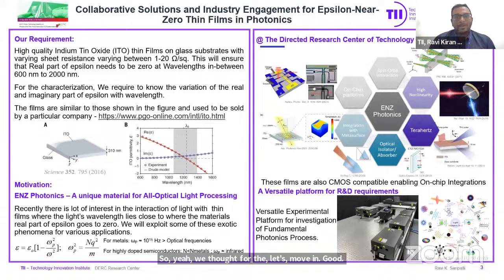What we require right now is high-quality indium tin oxide thin films with a sheet resistance varying between 1 to 20 ohm per square. And why do we need this? We want heavily doped semiconductors, essentially to bring the real part of epsilon to the visible or infrared wavelengths. So I will go back a little bit into our requirement, but the motivation behind this is a field